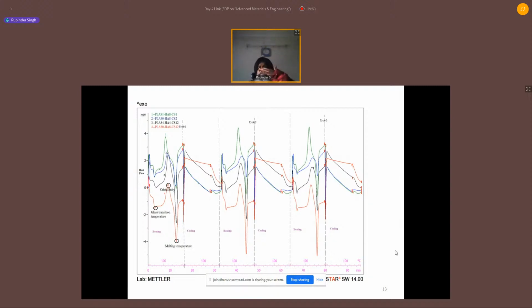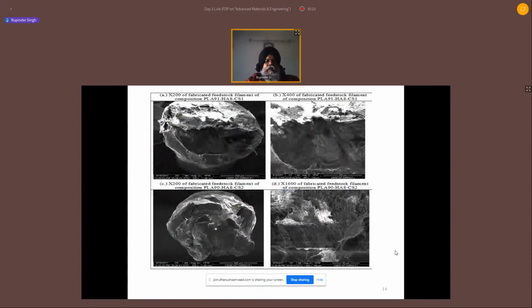So what we want to do with this type of study is this: I am using some particular implant or some particular material in particular environmental conditions, like it may be orthopedic, it may be dental. What will be the range of temperature conditions over which it will be working? So that we understand whether the material I have developed is going to be thermally stable or not. Keeping all these things in mind, we tried to understand for the different compositions whether this will be thermally stable, right? And then finally we did the microstructural analysis, which is based upon SEM-based optical photomicrographs. You can see in this picture that I got open porous and fibrous structures, which were really useful for the growth of the osteoblast cell.